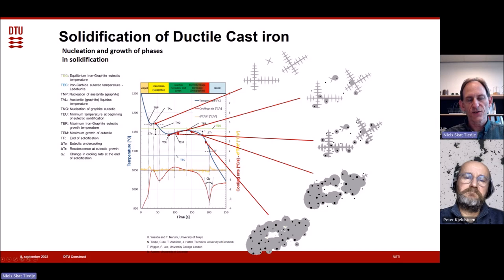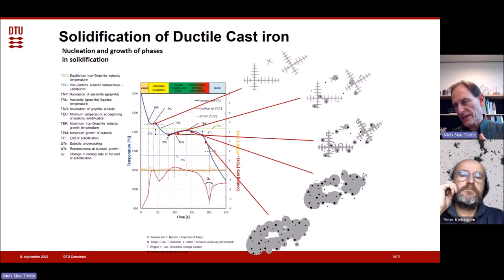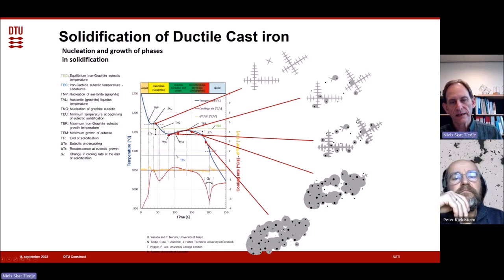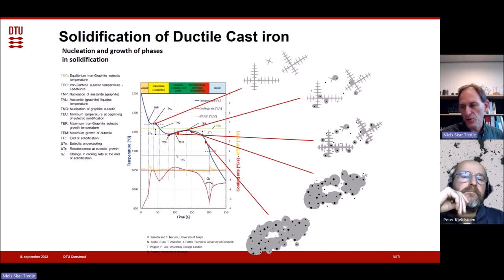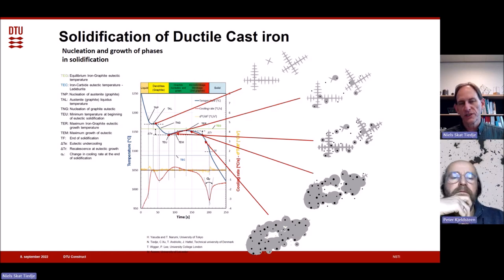So when the material begins to solidify, when the solid material grows, it evolves heat. At the same time, we are cooling, so we're extracting heat and we're evolving heat. It's always a balance between those two things. Graphite should form on the green line here, but graphite does not form easily, so you need an undercooling to start the nucleation. And this is the undercooling. By the time the graphite forms, you are so much below the equilibrium temperature that it grows really fast, and of course it releases energy.